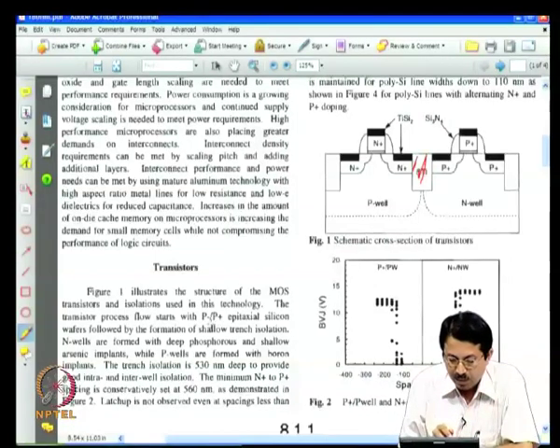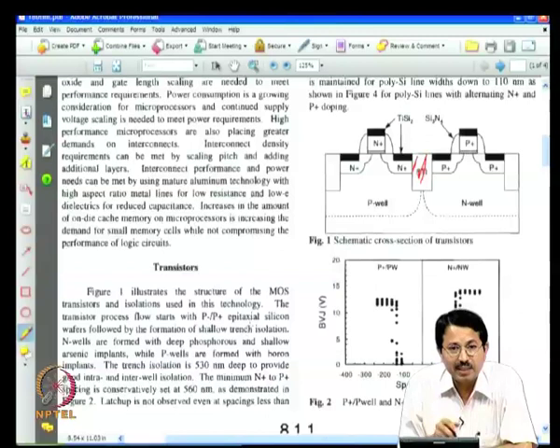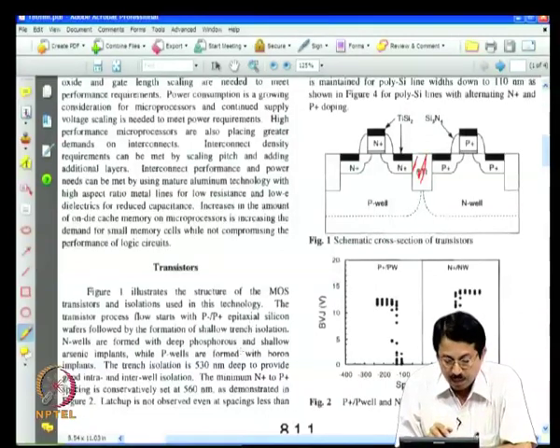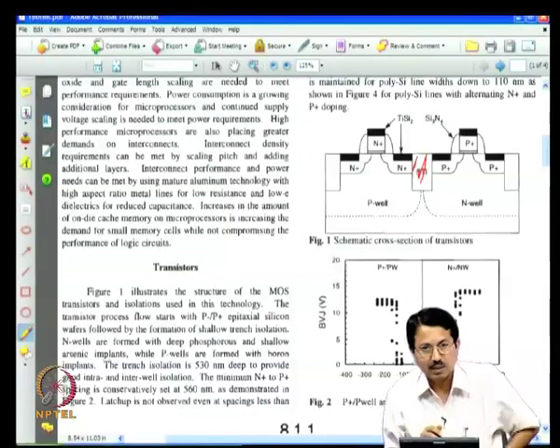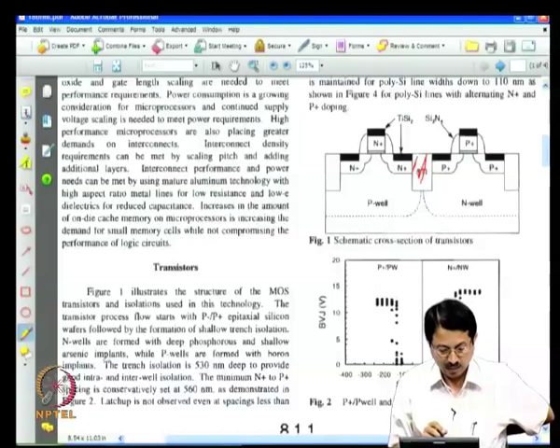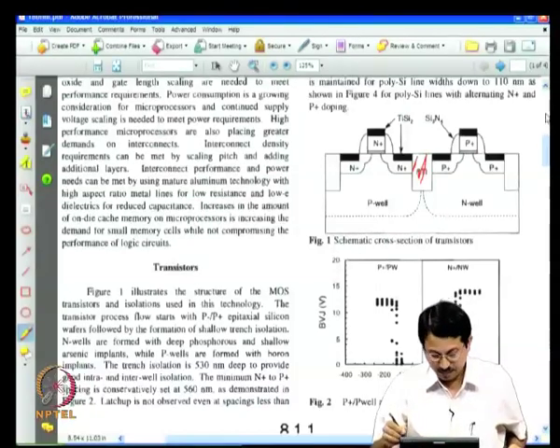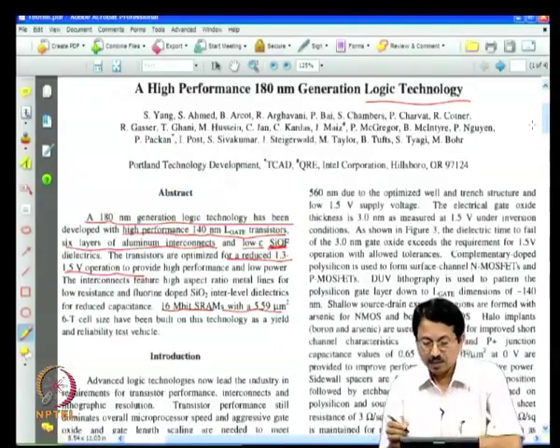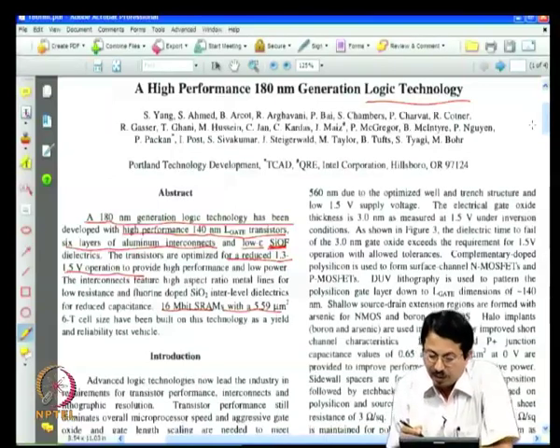Start with the P minus P plus epitaxial silicon wafers followed by the formation of shallow trench isolation. N wells are formed with deep phosphorus and shallow arsenic implants. They have not used in this particular case antimony and indium yet, but nonetheless they use phosphorus and arsenic combination for N well, while P wells are formed with boron implants. That is how they are forming these wells. And then they also have